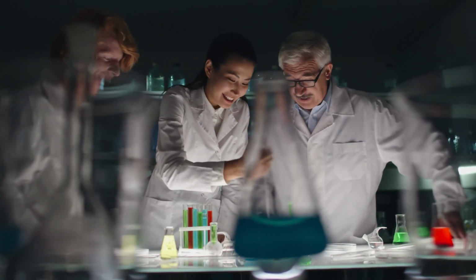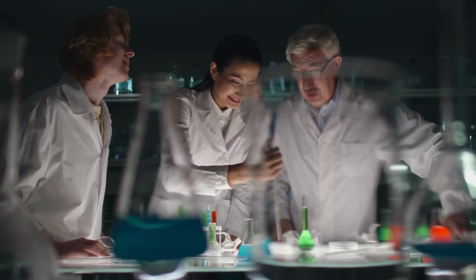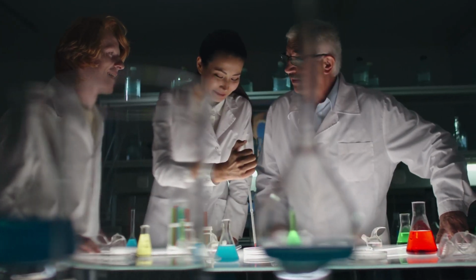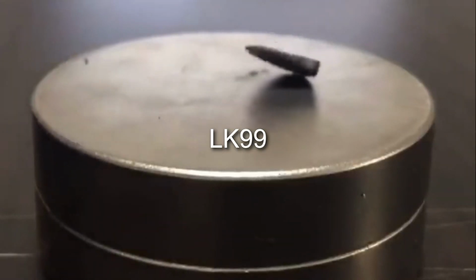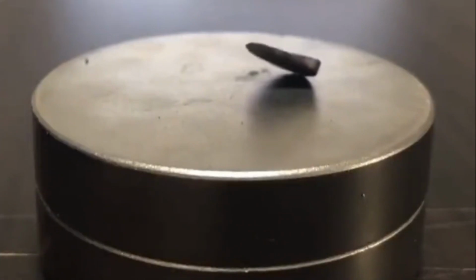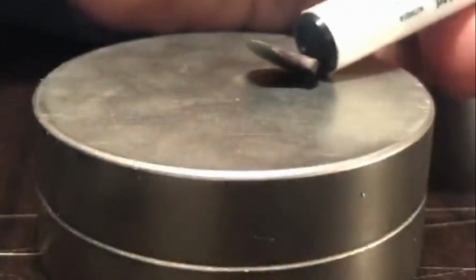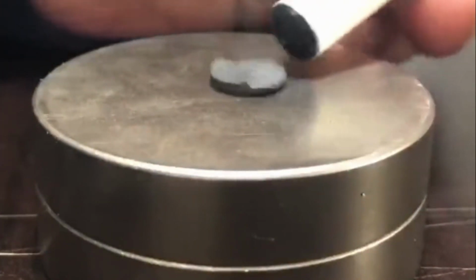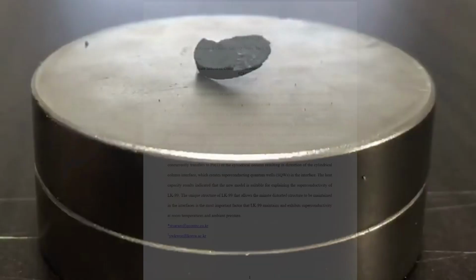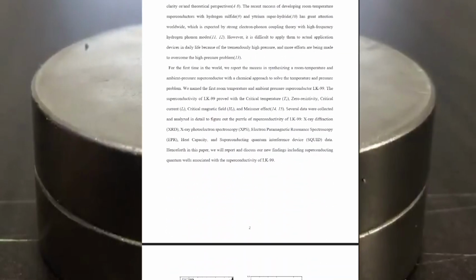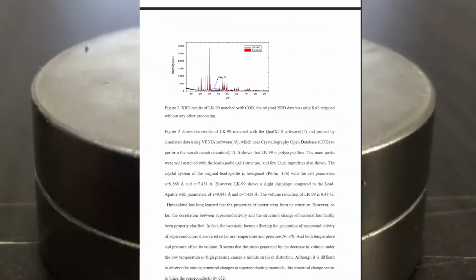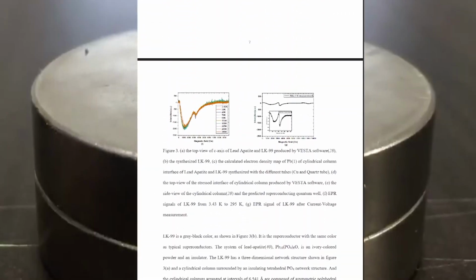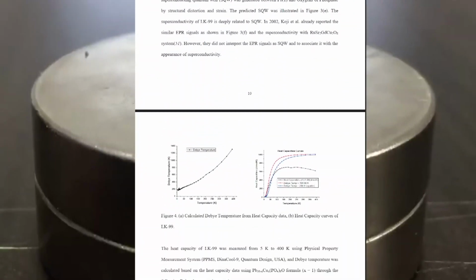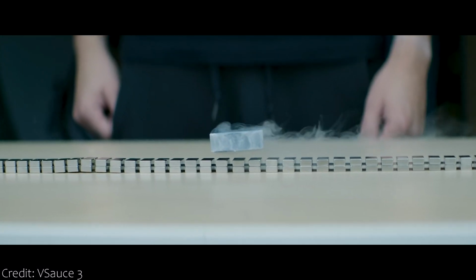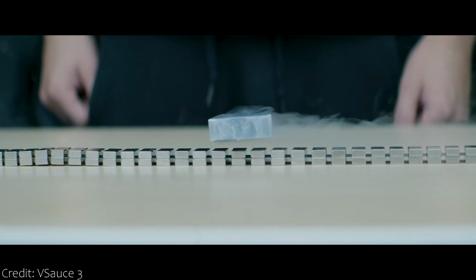So the smart people were looking around a bit more, and then they found another material which promised to be the holy grail, LK99. The name stems from the original research conducted by two Korean scientists back in 1999, where they discovered this material, Lee and Kim, hence the name LK99. Then in 2023, the sensation was announced that they had verified that indeed this material showed superconductivity at room temperature. And even the magnetic levitation effect mentioned before, the so-called Meissner-Oxenfeld effect, could be demonstrated.